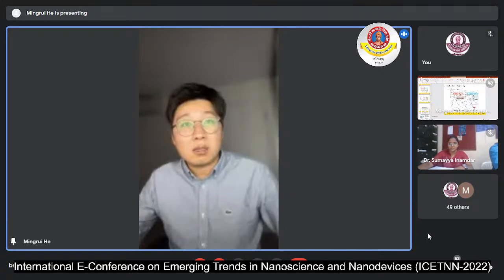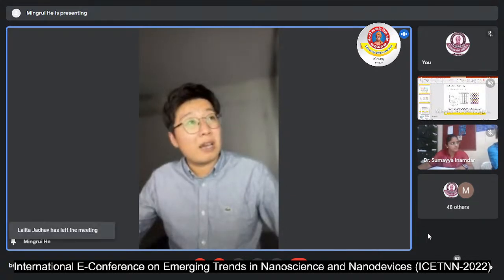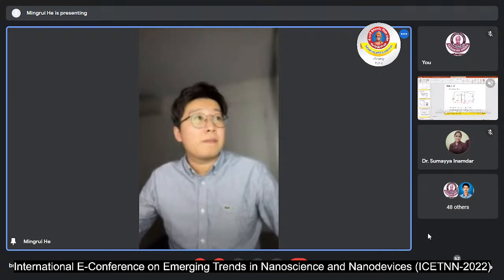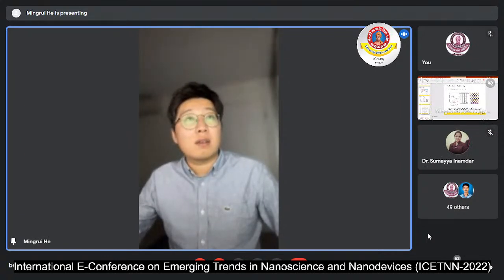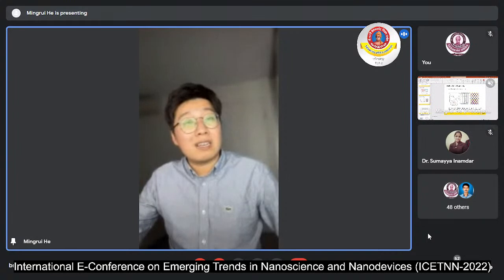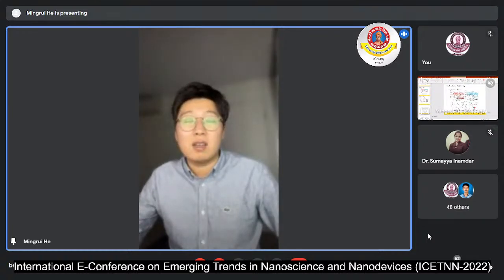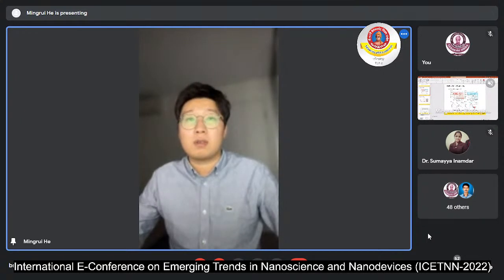So after that, we used defect DFT calculation, similar to this diagram. We found that theoretically, for the lithium-zinc antisite defect, the transition energy, meaning the activation energy, is around 90-something meV, which agrees well with what we measured here. So we confirm that this highly likely belongs to the lithium-zinc antisite defect. That is what we concluded in that paper.